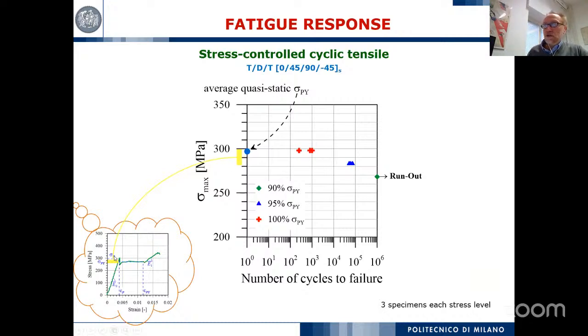This is the range on the static curve, and here is the fatigue life in terms of the maximum stress in the cycle. And then you can see easily that if we are at 90% of the pseudo-ductile stress, the beginning of the first peak, we have long fatigue life. We stop at 1 million cycles. But as you get closer to this pseudo-plasticity stress level, the fatigue life becomes shorter and shorter, and this means that the material cannot support this stress level for longer.